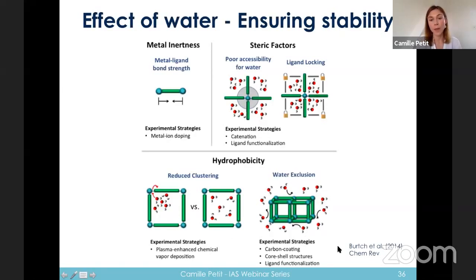In that review paper here, they highlight different strategies that have been used in order to ensure the proper stability of MOFs in the presence of moisture. So it can be ensuring that there is a strong bond between the metal and the organic linker. It can make sure that there is steric hindrance around the metal site, because that's in a way the weak point. It can also prevent clustering of water around that weak point, or make the material more hydrophobic, for instance, using carbon coating, or functionalizing the ligand with a hydrophobic component.